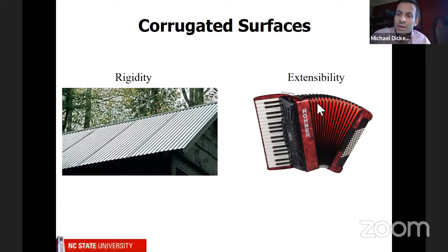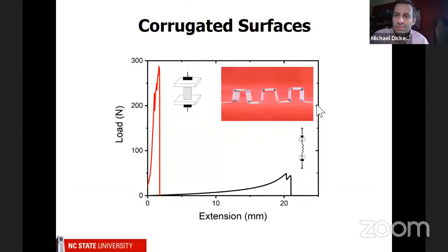Likewise, you can make materials stretchable simply by their corrugation. It has everything to do with which direction you're applying the stress. So in these very simple polymer sheets, if we corrugate it in one direction, we can make it very stiff, like 300 newtons or even higher. And if we corrugate it in the other direction, we can make it very soft and even stretchable.